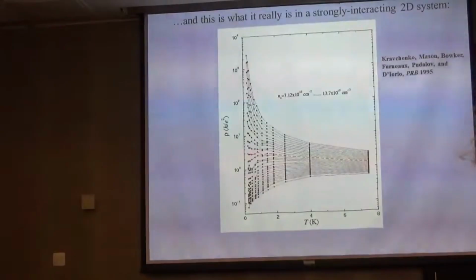But if you exceed some critical electron density corresponding to this red line, you have the opposite effect. At first, nothing happens, or maybe resistance grows a little, and then it goes down. And it's not a small effect, it's a factor of 10 effect. Okay? So it's completely unexpected, but it does look like a phase transition. It's critical behavior.